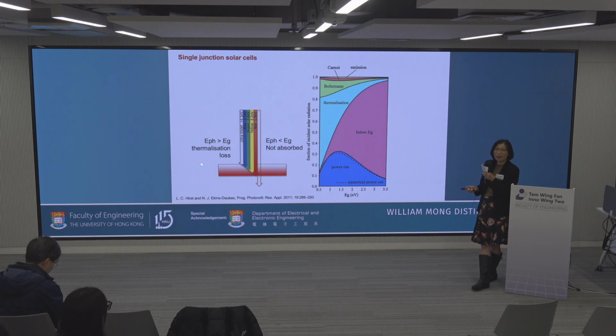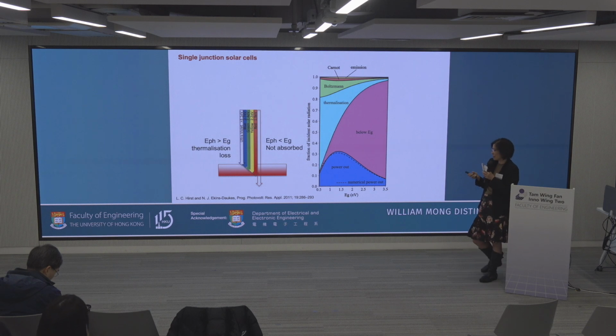The current technology, silicon, is based on one semiconductor material with a fixed band gap, and therefore light with energy higher than the band gap does not have all of its energy converted to electrical energy. A lot of it just turns into heat, so you have very hot modules and not very efficient modules. Then you also have light with energy lower than the band gap, which doesn't get absorbed at all. So you have the sub-band gap loss and the thermalization loss, and therefore the highest efficiency of a single junction is around 33%.